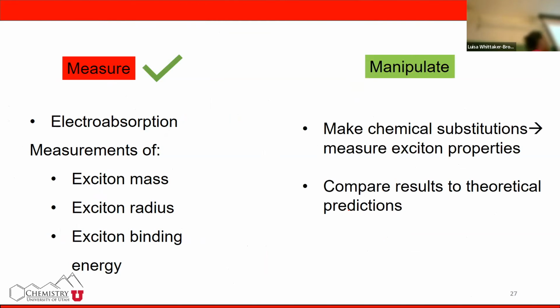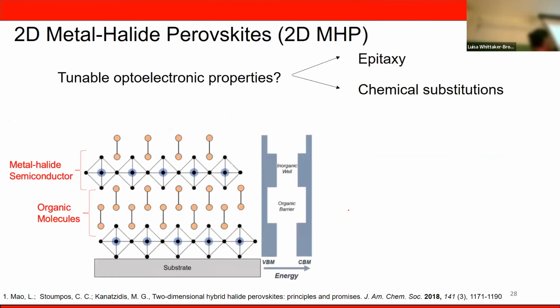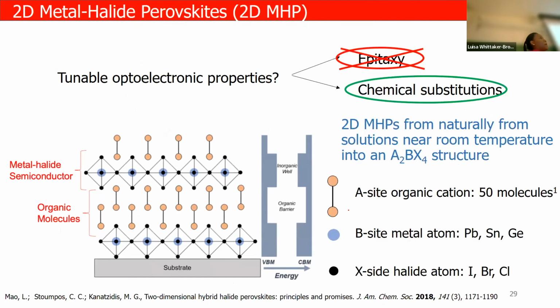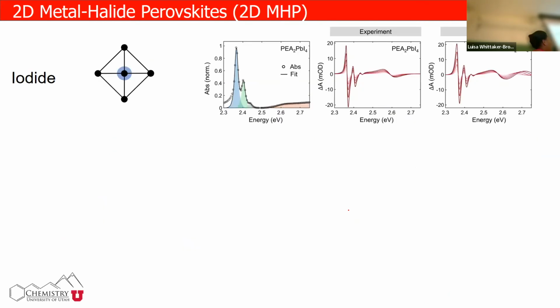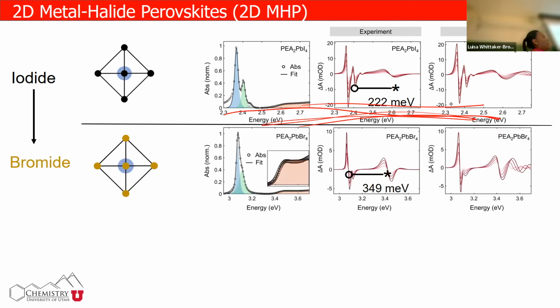Now we want to know if we can find ways to manipulate things. So the nice thing about perovskites is that it saves us about $1 million because we don't have to worry about molecular beam epitaxy, as we just need a $10,000 spin coater, okay? So that's nice, right? And it gives you a lot of opportunity to vary composition. So for the iodide, we do electroabsorption, and we have this right here. Then the binding energy is about 222 milli-electron volts. If you go to bromide, it increases to 349.